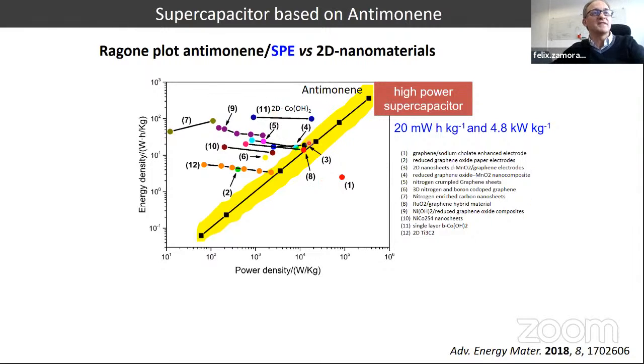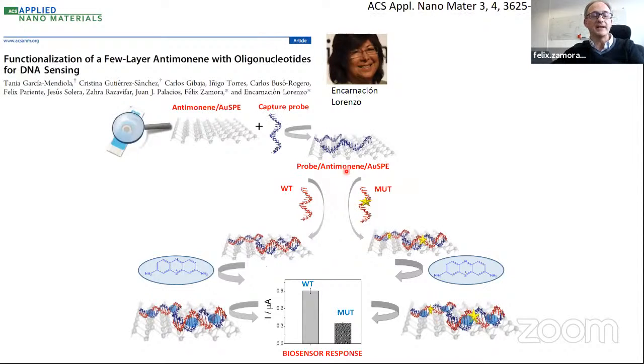I'm telling you that we plot here the Ragone plot between power density and energy density. Here, I highlight in yellow the result that we got with the different antimonene experiments, and in particular for low quantity of antimonene, we have exceptional values of power density versus energy density, telling us that we have a really high power supercapacitor in comparison with this long list of other 2D materials. Okay, so results were very promising despite we don't have a real device, because we have some problems building this big supercapacitor device.